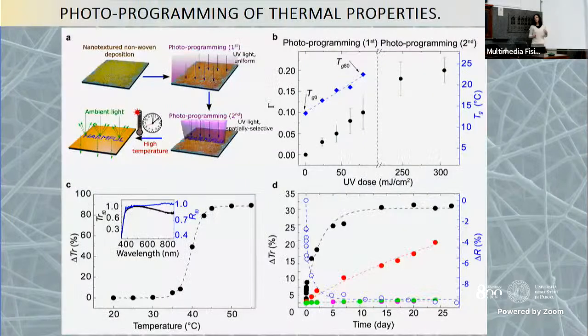So what we did, we make fibers, we deposit them on a surface. We then expose all the fibers to UV light. And this is the first photoprogramming step, which means that by choosing the proper dose of exposure, we can set the working temperature of the device.